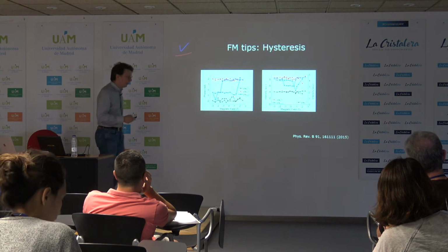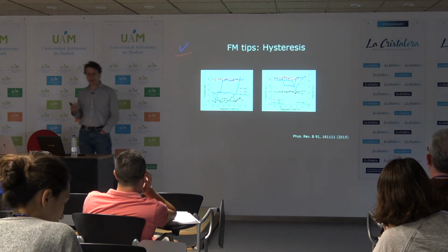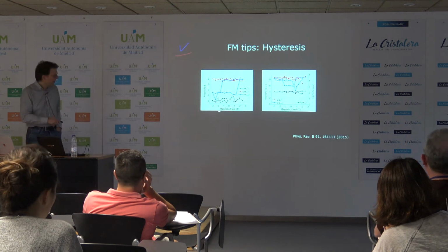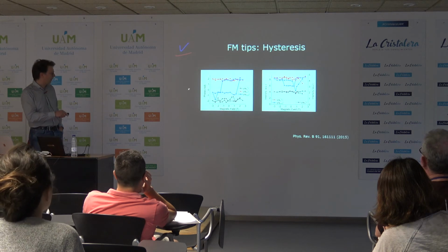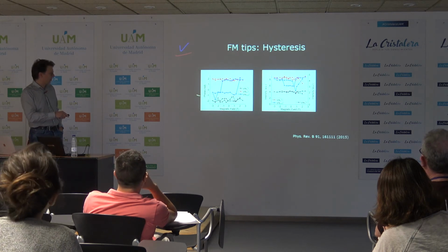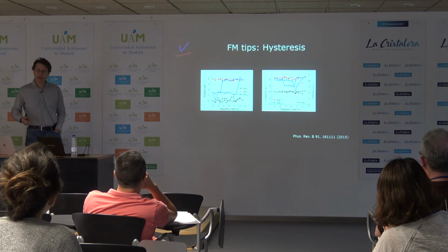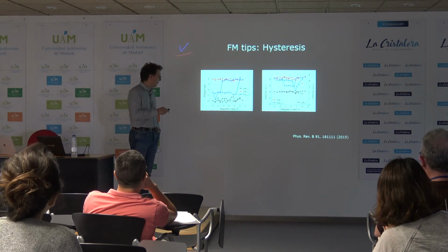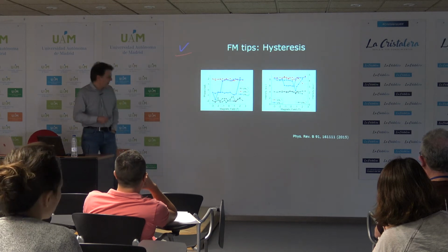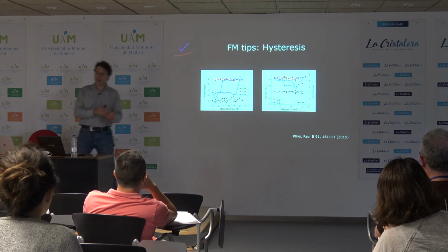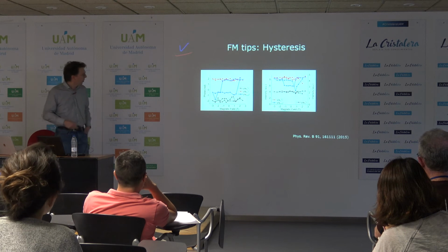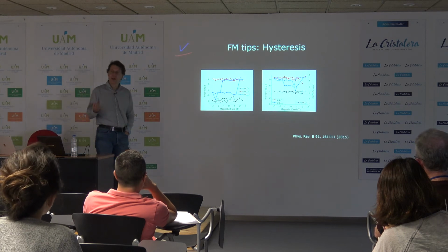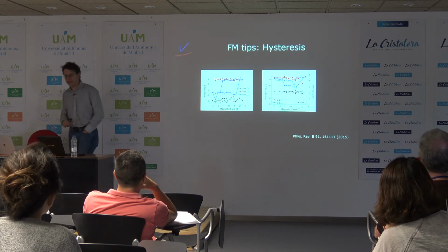Or we can make ferromagnetic tips, like the one of which I've just shown the data, where basically as a function of field we can essentially record a hysteresis loop of the tip if we subsequently record topographic images of our sample surface. And so basically by controlling how much excess iron we pick up or whether we pick up a flake of the material, we can control whether the tip is ferromagnetic or antiferromagnetic.